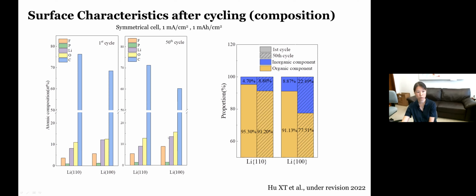And this difference actually becomes more substantial when you look at the results at the end of the 50 cycles. So here's a chart making a comparison. For the lithium-110, we actually have a higher amount of organic components and a smaller amount of inorganic at the end of both the first cycle and the 50 cycles. And more importantly, we do see more lithium fluoride forming in the lithium-100 instead of lithium-110. At first glance, this is a bit counterintuitive for understanding the electrochemical performance that resulted.